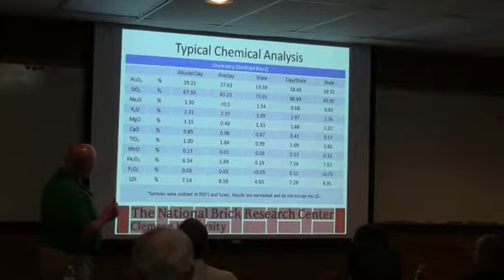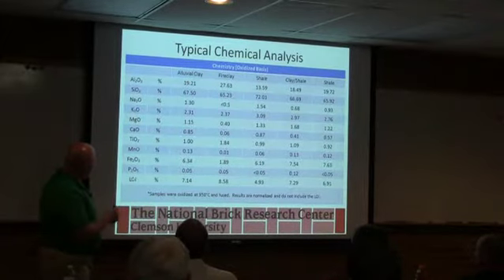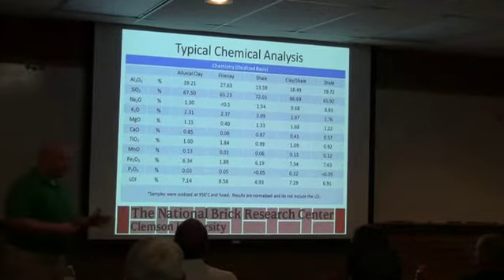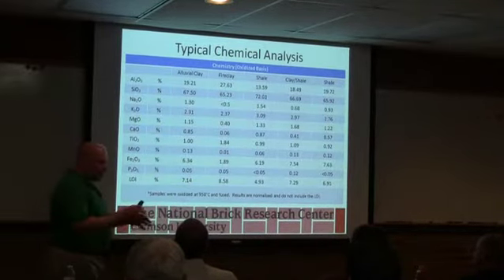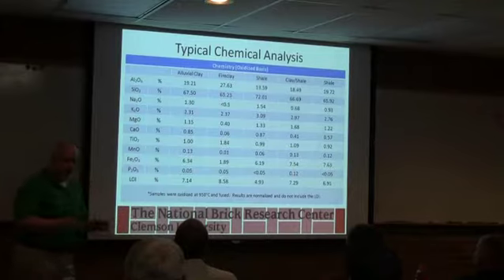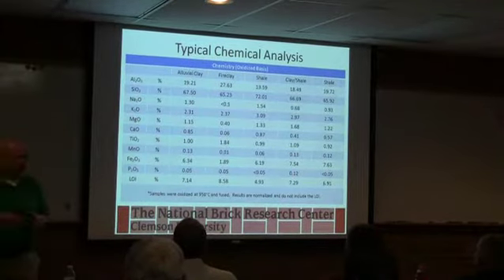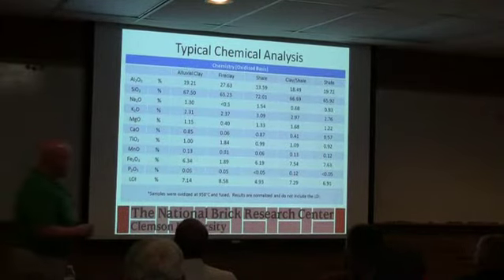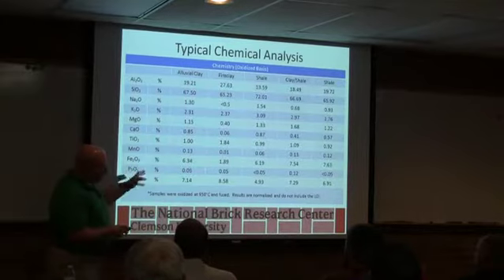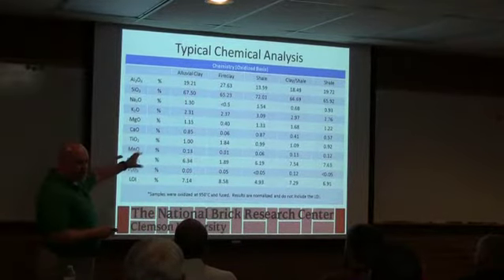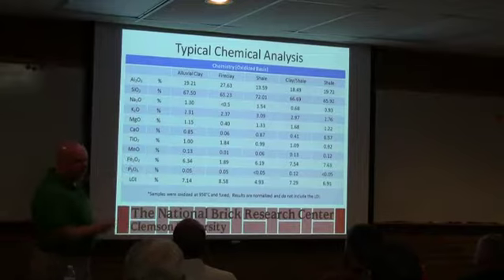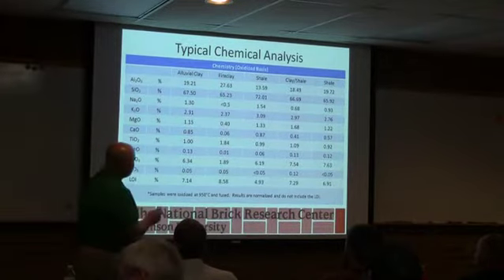Now, the one thing you have to understand when you do a chemical analysis, now this is telling you it's good to do particle size. Particle size tells you if there's going to be any big changes in the way the material flows through the extruder, shrinkage changes, things like that. Usually if there's a change in the particle size, there's going to be a change in chemistry too. And that's where things start to change in the kiln.